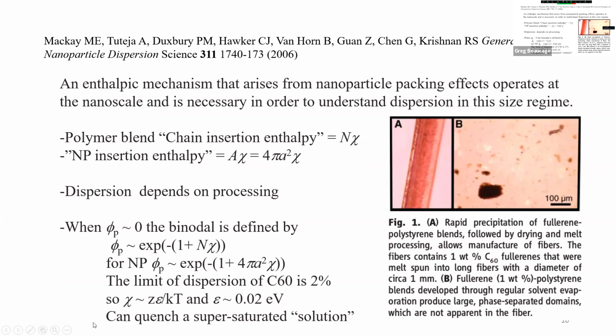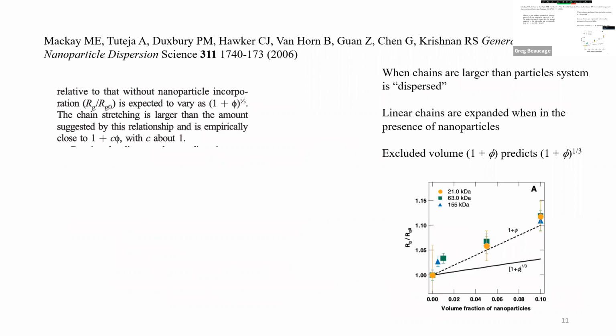And the chi value is like lower. It's polystyrene beads in a polystyrene matrix. Normally, a deuterated polystyrene matrix with hydrogenous polystyrene has a positive chi. Those are somewhat immiscible. But his is negative chi, so his is miscible. So by putting the polystyrene into this bead form, he's made it miscible with the deuterated matrix. And from that, you can predict a phase behavior out of this thing.